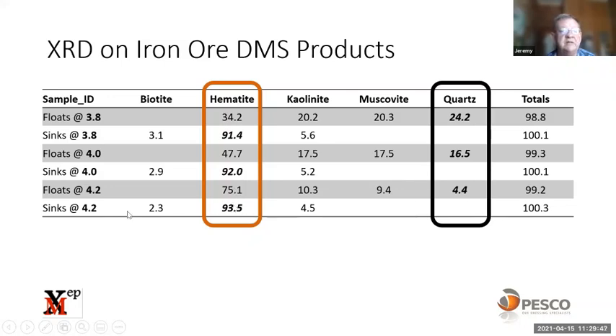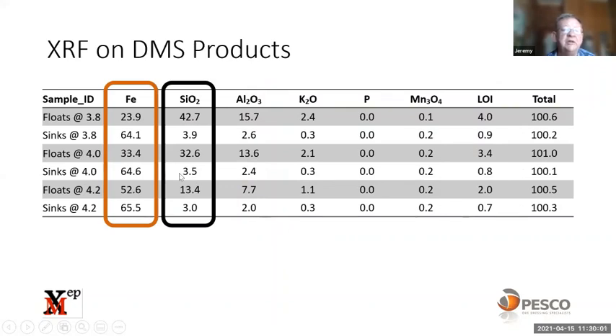If you look at this at 4.2, we'd expect almost all hematite, and you can see there 93.5% hematite, not reporting any quartz in there, interestingly enough, and a bit of kaolinite. If we look at the corresponding XRF, the Fe value of the sinks went from 64.1 to 64.6 to 65.5, and the silica dropped from 3.9 to 3.5 to 3. And that's just one of the things that one must remember with XRD. It has a lower detection limit, normally somewhere around 3%, below which it struggles to identify. So you can't use XRD to pick up minerals present as trace elements.